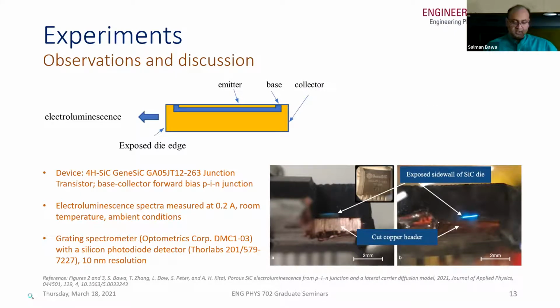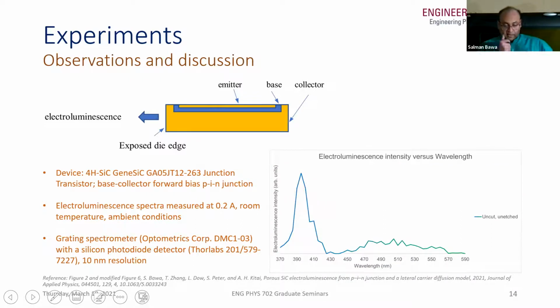On the right of the screen, what you see is we removed the packaging of the transistor. And so you can see this blue-green light that we were able to achieve at forward bias 0.2 amperes. And this electroluminescence spectra that you see on the screen is what we got. What we got is an expected narrow peak at the blue region and a broad green emission. And let us try to figure out why we're getting this.